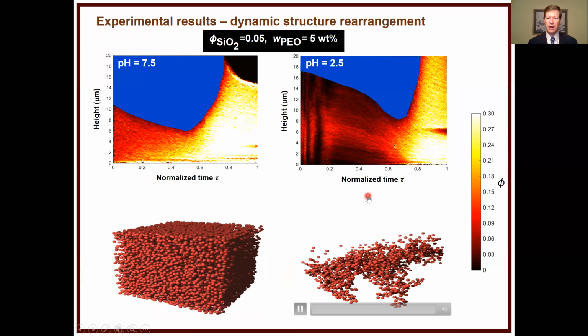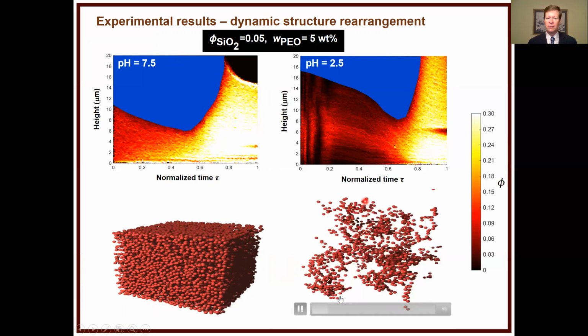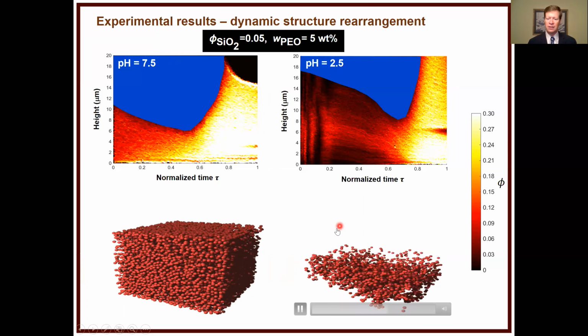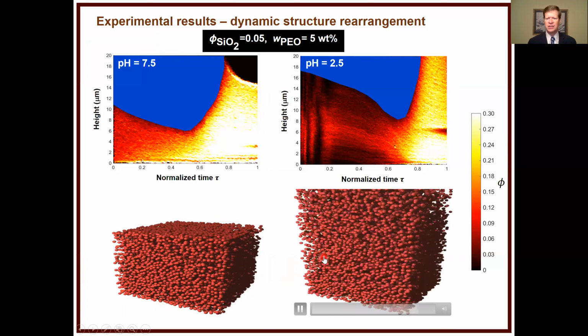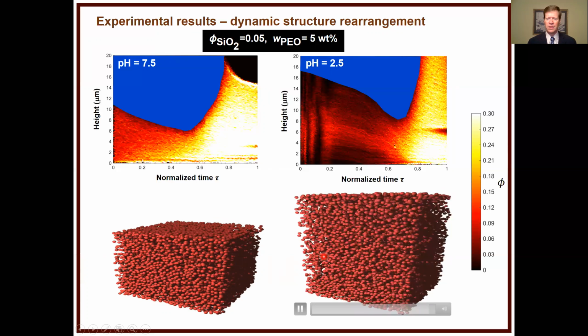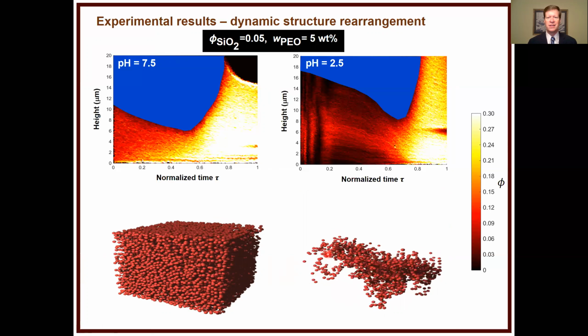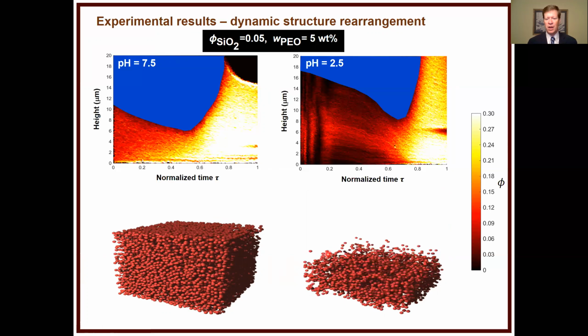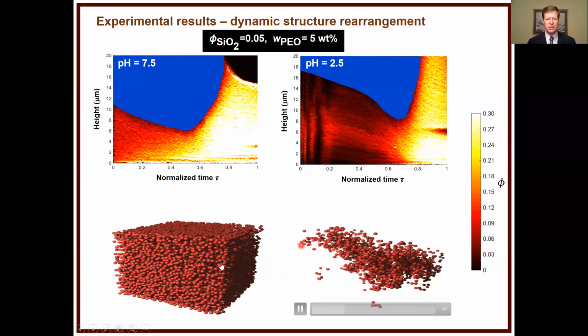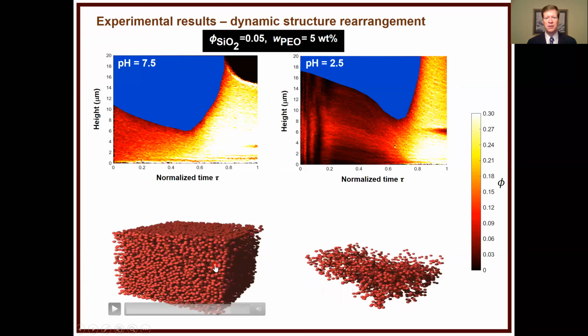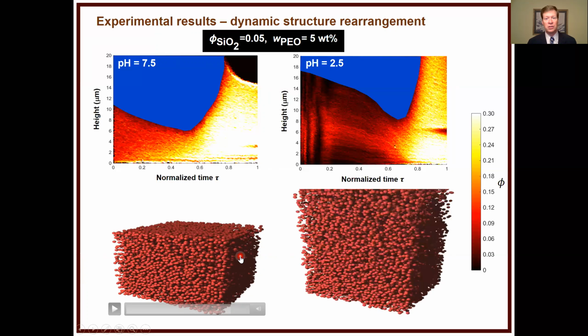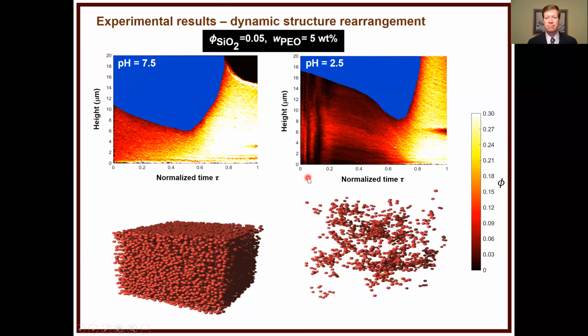In contrast, on the right, you can see something that looks like a very heteroaggregated gel with a very open structure that's changing very dynamically in time. We call it a tempest in a teapot. As you can see this grow and then settle, the microstructure starts to look similar, but we'll show you some very subtle differences that you get because of the nano precision of finding these particles in our experiments.